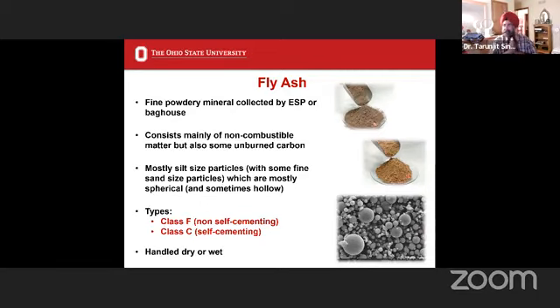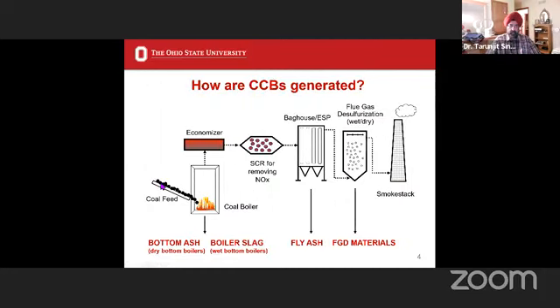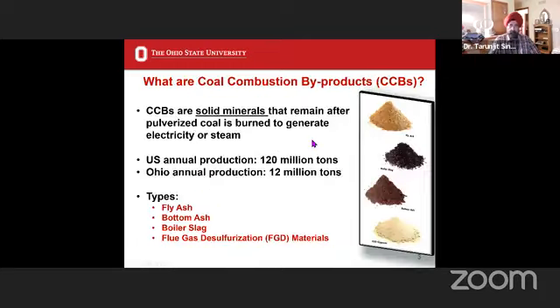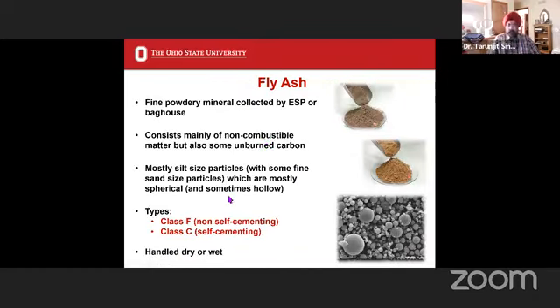So here is an example of a material which is human generated, right? It is not naturally generated, and it has the particle size distribution of silt, but does not have cohesion. It does have some apparent cohesion when it's wet, but that cohesion isn't very much at all. So class F fly ash, whether dry or wet, only has friction and no cohesion. And class C fly ash, if it is not wetted, only has friction. And once you wet it, it will have both cohesion and friction. Both these materials have some amount of unburned carbon. As you can see, the coal that was coming into the boiler has some unburned carbon that comes along, and that's why this also includes unburned carbon.